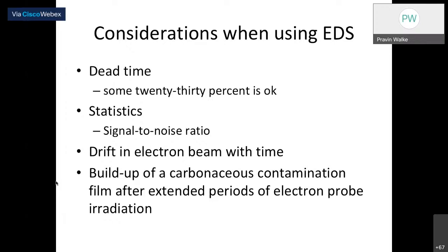So what has to be considered when you are using the EDS? If you are using the EDS system, the dead time, right? Dead time means how long you bombard the beam on your surface, and the delay between the X-ray signals reaching the detector and the bombardment, is very important, and that should not be more than 20 to 30%, right? Further, the signal to noise ratio: if the beam energy is very high, you will have very noisy signals, right? If your beam energy is low, it further delays the process, but at the same time the signal to noise ratio is improved, right?